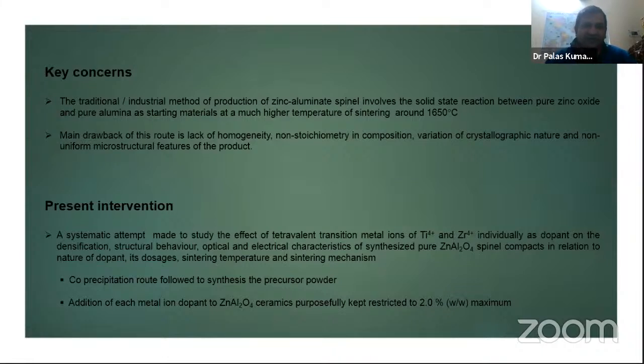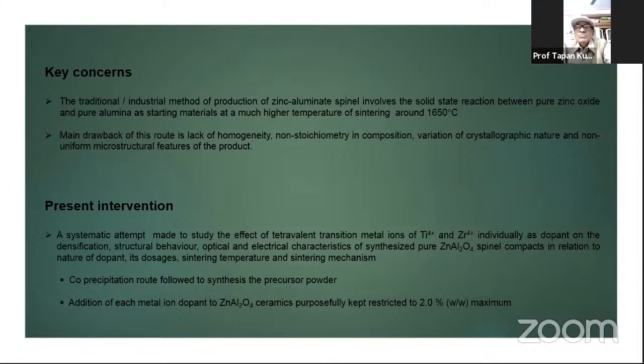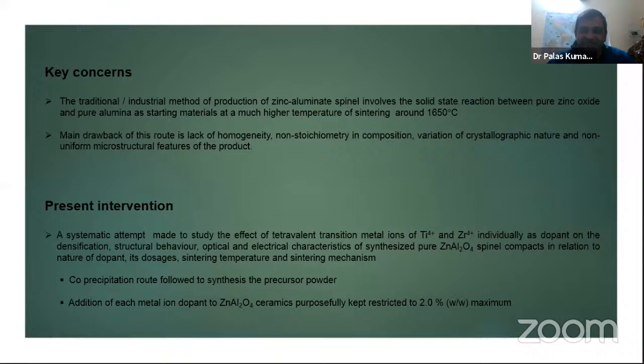And in our present investigation, basically, we studied the effect of titania and zirconia separately in the zinc aluminate matrix on the densification, structural, optical, and electrical properties. And regarding this, two points are noted. We followed the co-precipitated route for the preparation of the precursor powder, where we restricted the dopant concentration up to 2% in order to avoid adverse effects in the matrix.